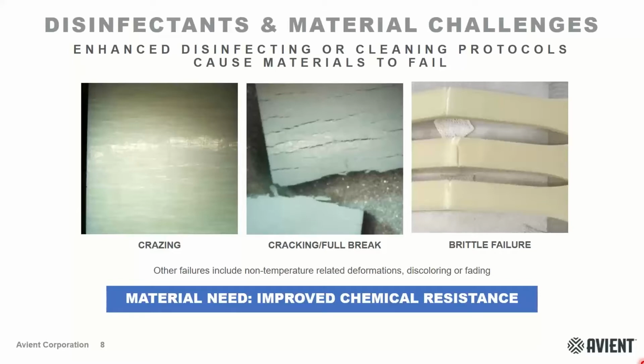So what types of actual problems do these disinfectants pose to materials? Below in these images, there are a few pictures of what can happen when a material is exposed to a disinfectant. And these are tensile bars in a lab setting where we put them in a strain jig and treat them with a disinfectant. In the image on the left, what you see here is crazing. Crazing happens because you have these little microvoids forming perpendicular to the stress. And those microvoids will start to propagate, and it'll appear as these little lines going across the bar. As crazing develops and these microvoids continue to grow, eventually it'll crack, such as the image shown in the middle here. You can see very obvious cracks to the naked eye. And as those cracks propagate, it'll also lead to a brittle failure.